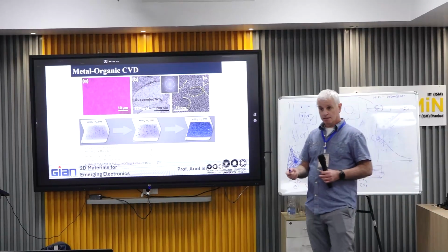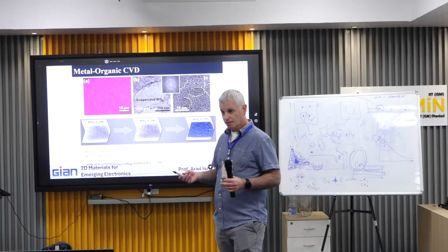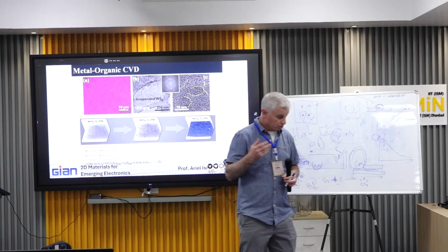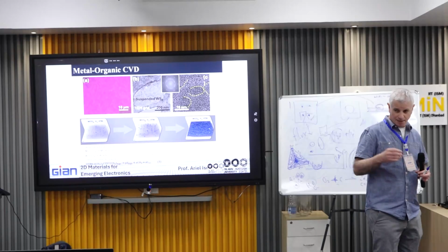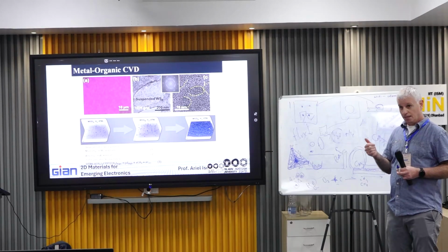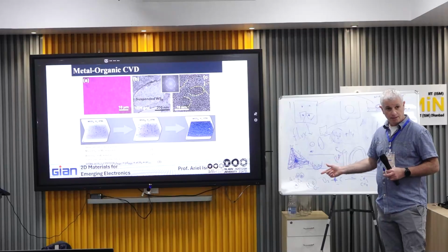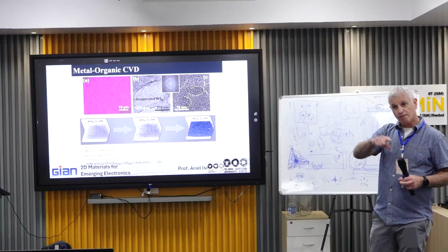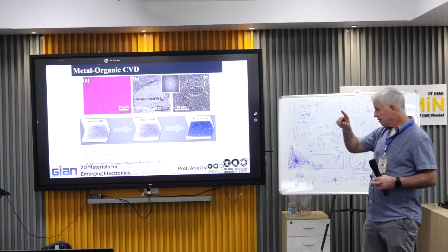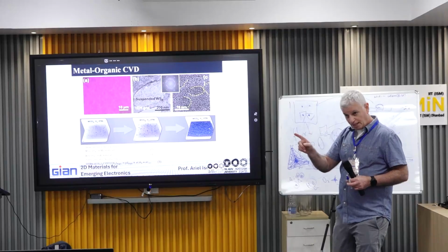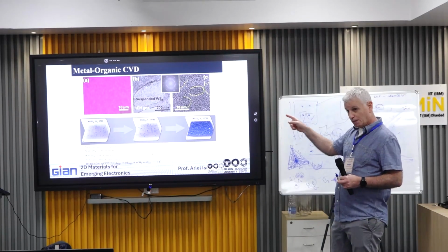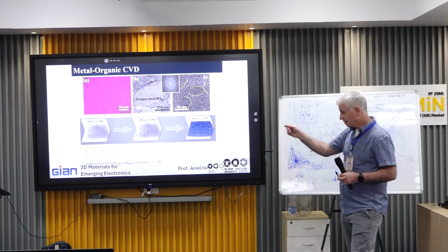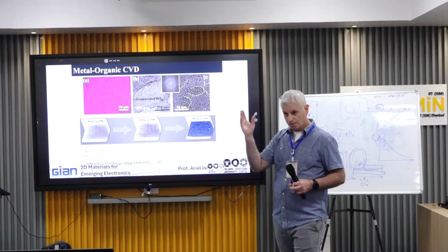Why? These are MoS2 or tungsten disulfide that, at the temperature of the growth, are supposed to be stable. But think about that first: they are monolayers. And second, they are defective. And thus, they react with the oxygen to form both sulfur oxide, that is a gas, and molybdenum oxide, that is not a gas, but at such temperatures, we know that it evaporates, like in the metal oxide CVD. And in this case, it's a monolayer, so for sure it's not stable.